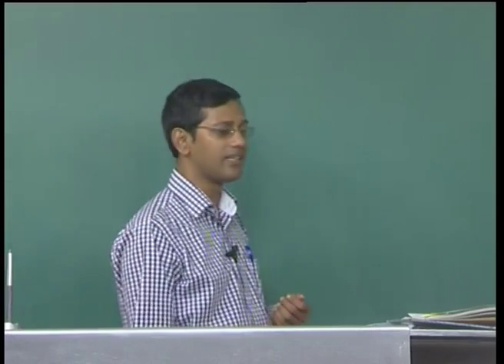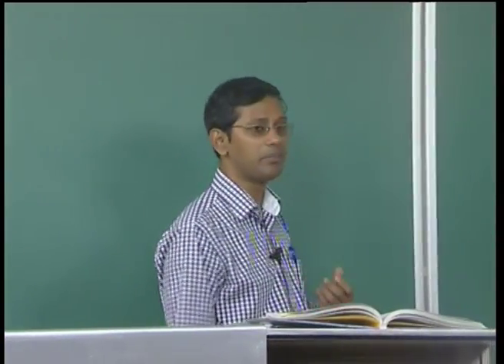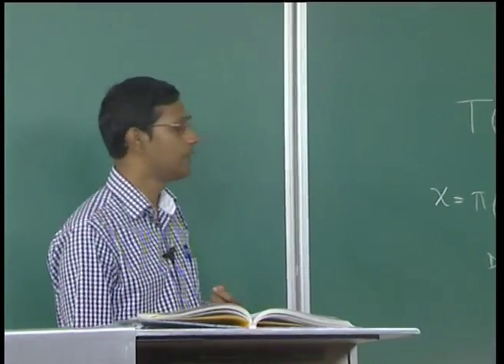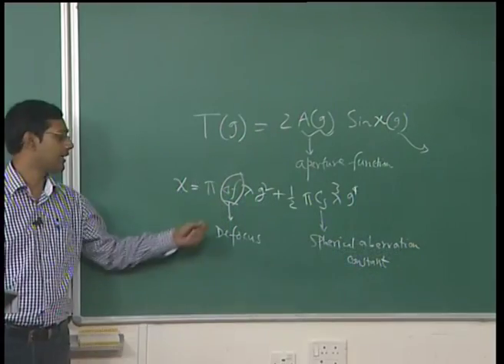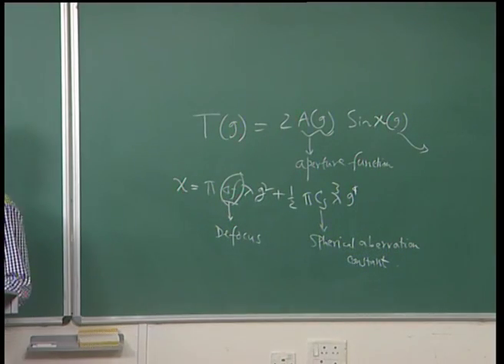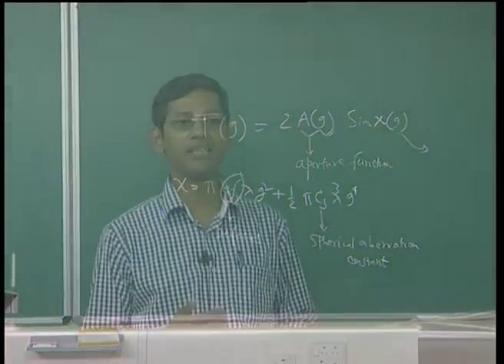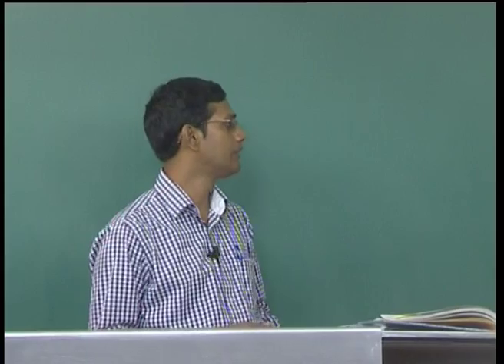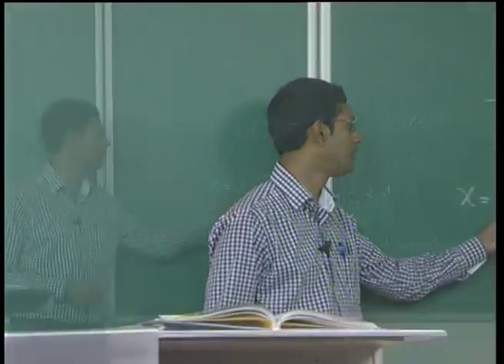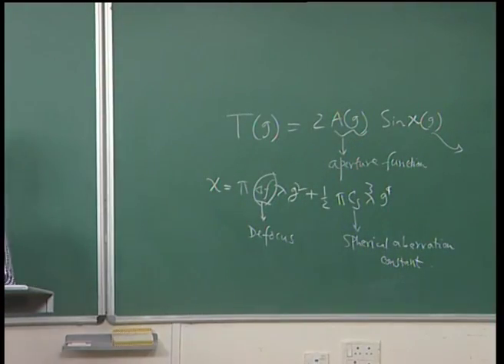So knowing that Cs is fixed for a particular microscope, the free parameter which can play the important role is delta f, the defocus, and that is where we showed you how this function can change using different values of Cs and different values of defocus. We discussed this factor in detail and found the optimum focus limit for high resolution microscopy.